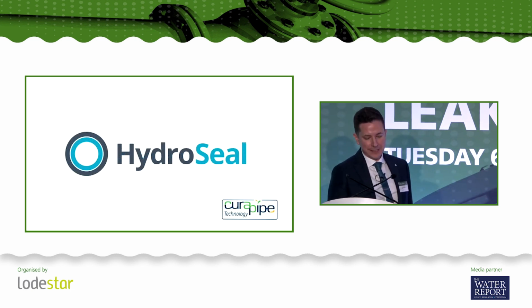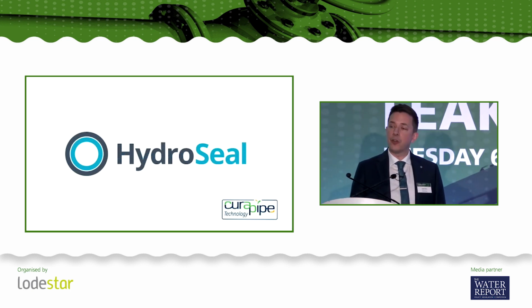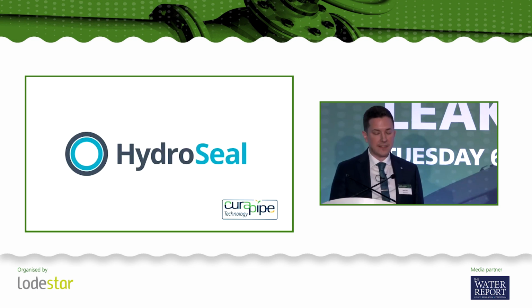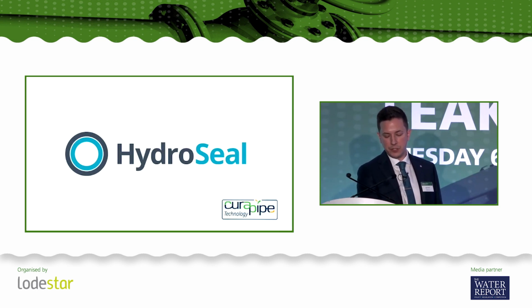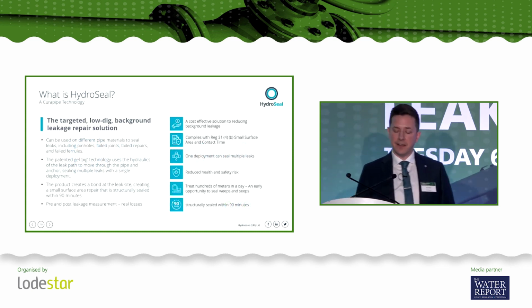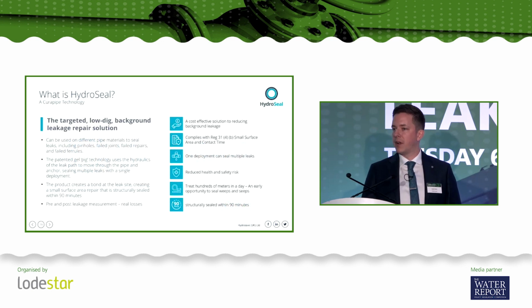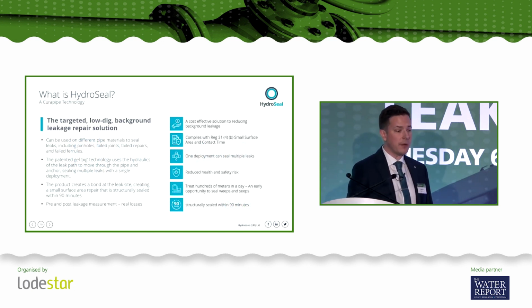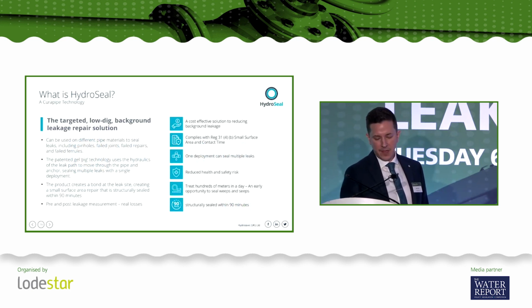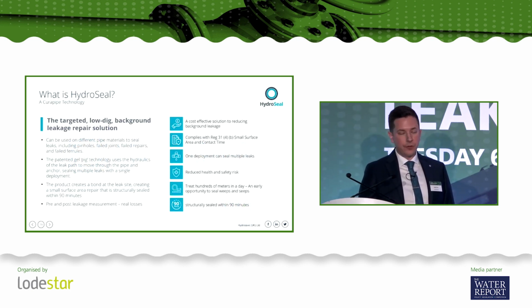So, what is Hydroseal? Hydroseal is based on Curapipe technology, developed in Israel with Israeli government funding and EU funding, but it's a targeted low-dig background leakage solution. Primarily a main side solution, although it can be used for larger private pipe work and longer supply pipes as well. What does it do? It creates small surface area repairs. It's not a liner. It can be used on all of the different pipe materials, and it can be used on the different types of leaks, whether it's pinholes, joints, longitudinal cracks, splits, circumferential breaks, displaced O-rings, seals, or failed joints on PE or asbestos cement pipes.